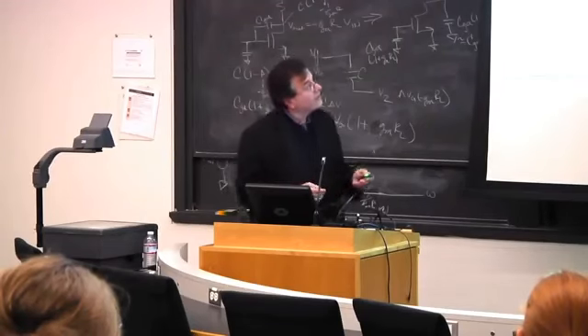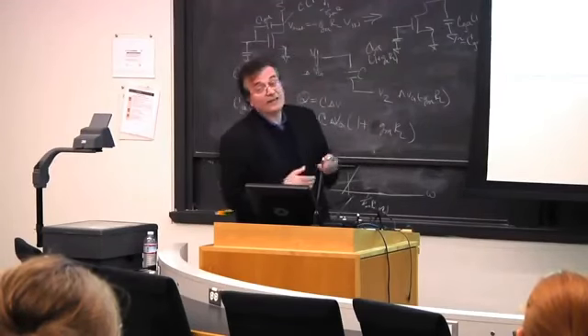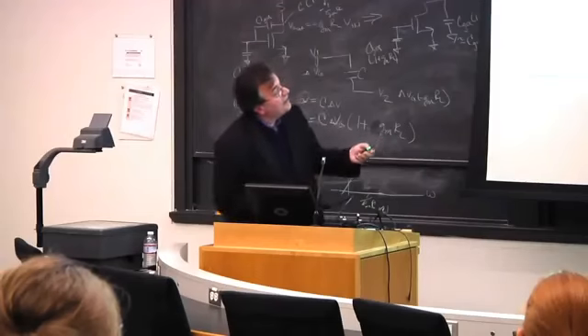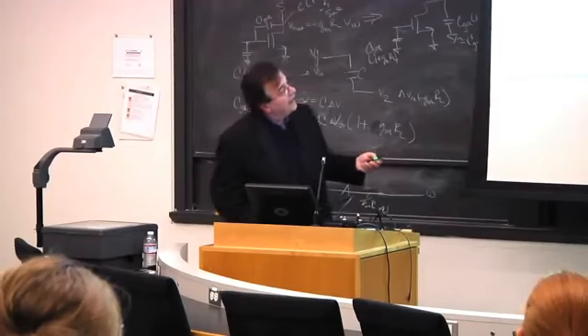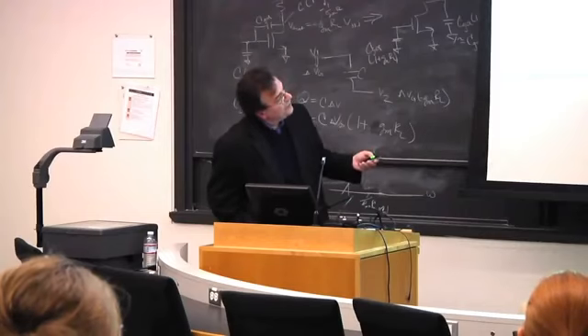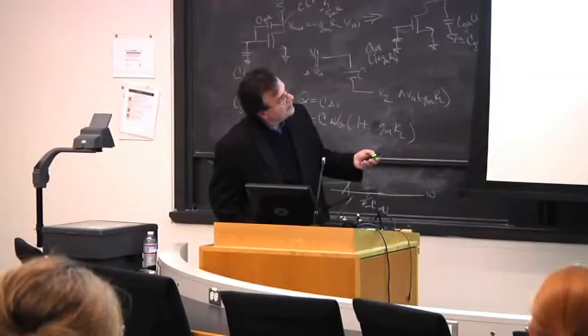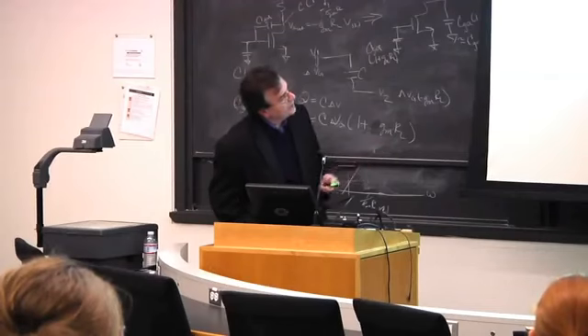So we found this system, lead telluride, lead sulfide. And this is the phase diagram. And so this is 100% lead telluride. And if you start adding sulfur, at first you have a region that appears to be a solid solution. And then you enter a precipitation region where lead sulfide precipitates. And then another region where you add more, and it's this spinodal decomposition region.